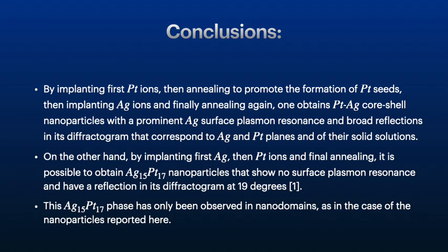In conclusion, we can affirm that by implanting first Pt ions, then annealing to promote the formation of Pt seeds, then implanting Ag ions and finally annealing again, one obtains Pt-Ag core-shell nanoparticles with a prominent silver surface plasmon resonance and broad reflections in its diffractogram that correspond to Ag and Pt planes and to those of their solid solutions. On the other hand, when one reverses the implantation sequence and performs no intermediate annealing, the Ag15Pt17